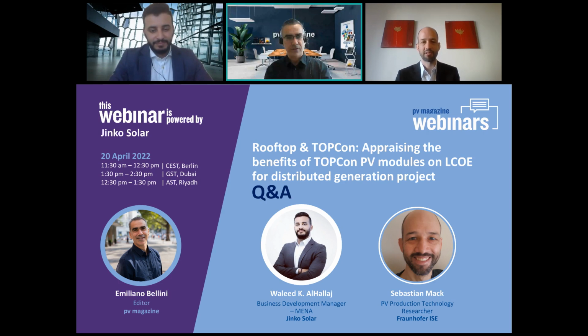So my feeling is we're already at above 24% efficiency of solar cells in production. I think this will increase to over 25%. The learning rate has been quite constant, with 0.5% give or take efficiency increase per year. So this means probably the lab record efficiencies that we have seen of over 25% might be seen in production within the next 2 years.